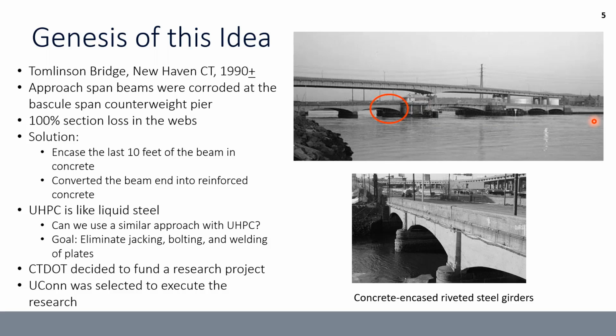Our inspectors went out there and found literally 100% section loss on every beam end. To this day, we're not sure why this bridge didn't have a more major failure, but it was discovered and we had to do an emergency repair. And the idea we came up with was essentially to convert the last 10 feet of the beam into a reinforced concrete beam. We essentially encased the beam in concrete with a lot of reinforcing steel, and converted it to a concrete beam end. Very successful repair, worked very well.